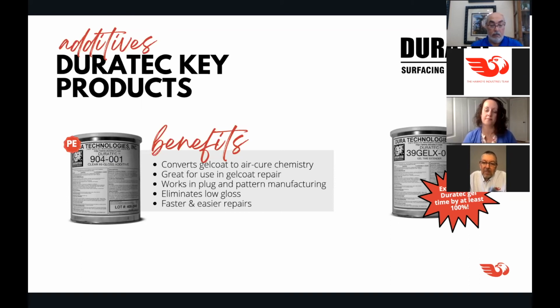This will about double the pot life of your material. It doesn't affect the sprayed out material near as much, but what's in your gun, what's in your container will about double in gel time. So it goes from, at 77 degrees, 15 minutes or so to 30 minutes or so. When I'm doing training classes, I use this product extensively because it is very forgiving. If you've got 15 minutes, you've got to get all that gun emptied quick, and you're not typically using best practices to get there.